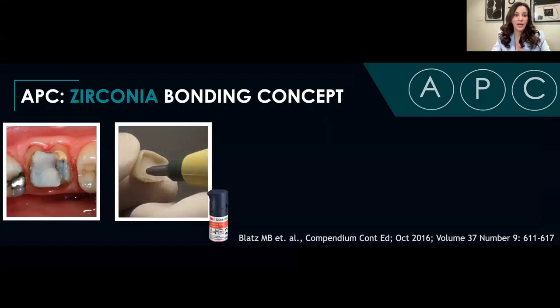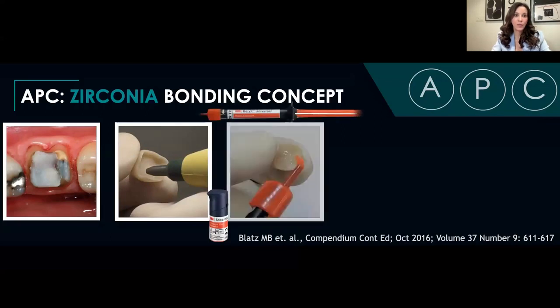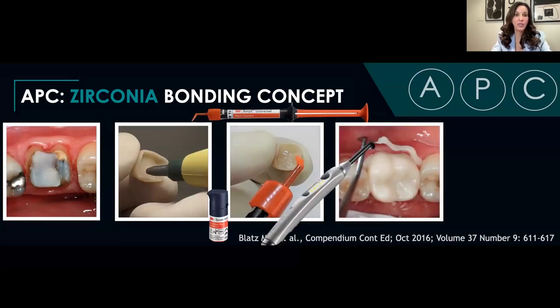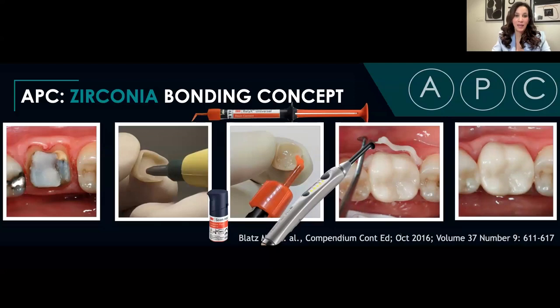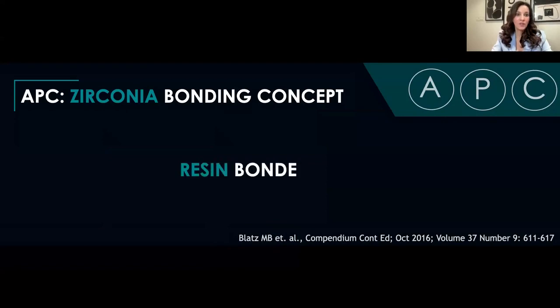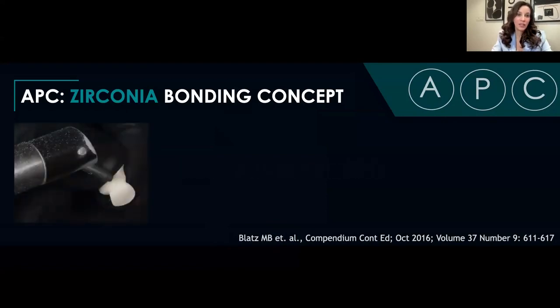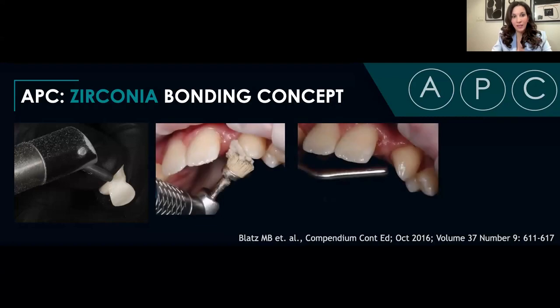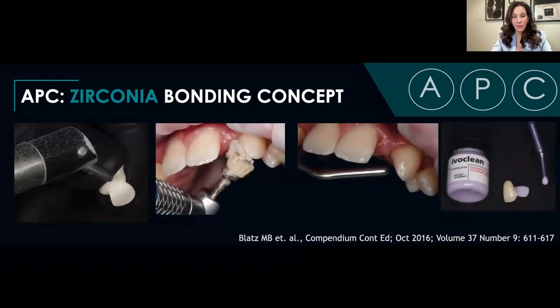So you air abrade, and then you can use a primer if you want to use a primer. But the self-adhesive cement has the MDP primer already in it, and these are just some examples of primers you can use. Then you load your crown with the self-adhesive cement, seat it, and if it's a dual cure, you can cure the material, or it's an auto-cure material as well. What about a resin bonded bridge? This is another indication. So this is a case where we made a single wing zirconia-based resin bonded bridge. So what you're looking at here is sandblasting or air abrading of the single wing, cleaning off of the abutment tooth, and then, sorry about that.